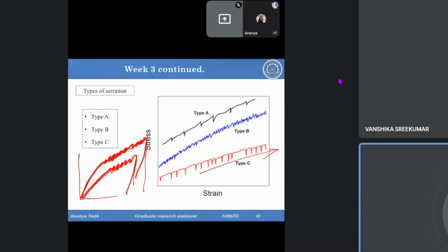It already has the characteristic of showing serration at room temperature, and the strain rate range for DSA is also so small. So obviously for aluminium it's a common phenomenon. For steel it's a rare phenomenon, because steel needs a lot more strain rate and the temperature is also very high, 250 or 300 something. So what is your question now?